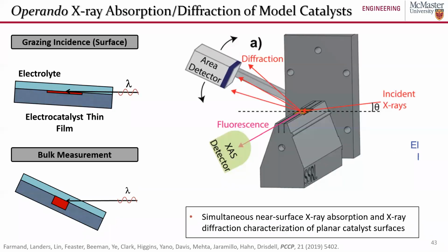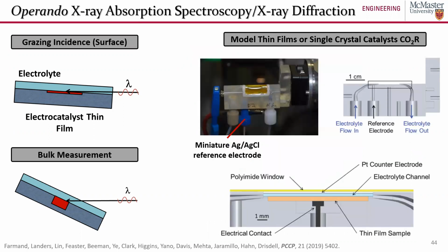For these measurements, we're doing combined X-ray absorption spectroscopy using a fluorescence detector, and we are also doing X-ray diffraction using an area detector. So we had one detector off to the left of our electrochemical cell, and an X-ray diffraction detector that was kind of looping around the top of our electrochemical cell. And so we had some significant geometrical constraints when we were designing and using these cells. This is essentially what the 3D printed electrochemical cell looked like. This was designed by a beamline scientist at SSRL named Ryan Davis. But because we were so geometrically constrained, we only had a very small area where the reference electrode could be inserted into this electrochemical cell.